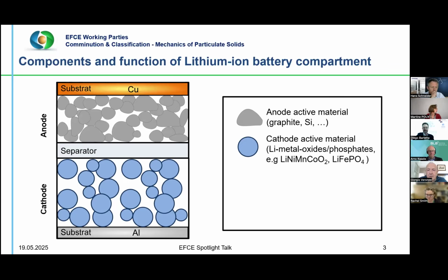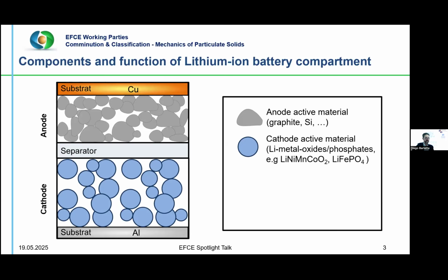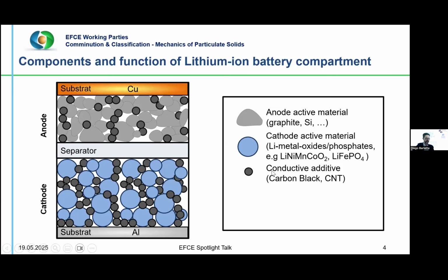Common cathode materials include lithium nickel manganese cobalt oxide, NMC, often with particle size around 500 nanometers, known for its high energy density, and lithium iron phosphate, which can have varying particulate forms, including nanorods of 30-50 nanometers or larger particles around 3 microns, valued for its safety and cycle life.